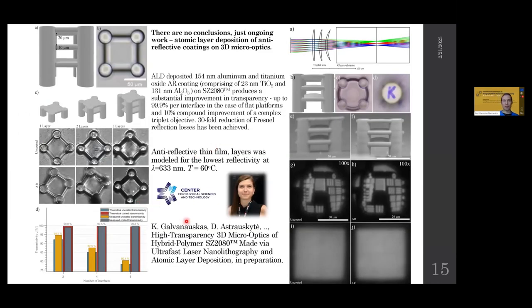The coating work was done in the Center for Physical Sciences and Technology in Dr. Linas Grinevičiūtė's laboratory, and it showed that both the platforms or flat surfaces have a significant increase in transparency, reaching almost the theoretical threshold, so no light loss depending on the number of layers. For this purpose, we tested 1, 2, and 3 layers.